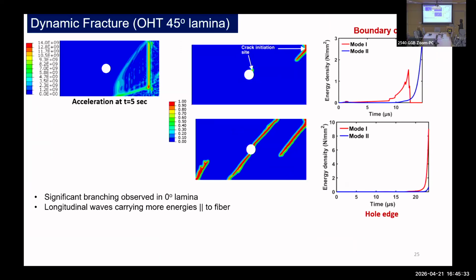So same simulation, but with 45 degree fiber orientation. Once again, we see the crack starts from the boundary, but quickly the crack emanating from the hole edge picks up, and you see the propagating wave front was not as homogeneous as the one we saw in 0 degree, which is quite expected because now the fibers are oriented at an off angle. It's a 45 degree lamina, right? If we look at the energy spectrum, we will see a similar situation. In this case, it was mode 2 driven in the corner when it initiated, but at the hole edge, it was primarily a mode 1 driven crack. So it was essentially matrix cracking along the fiber direction, parallel to the fiber direction.